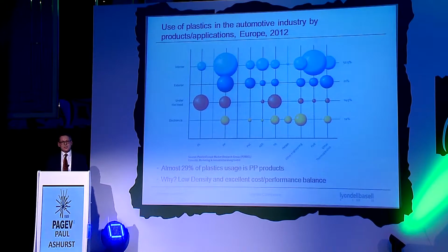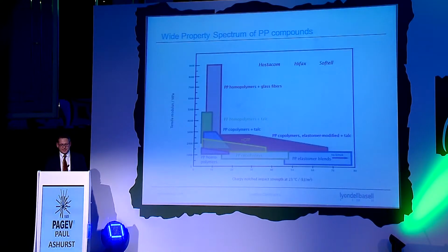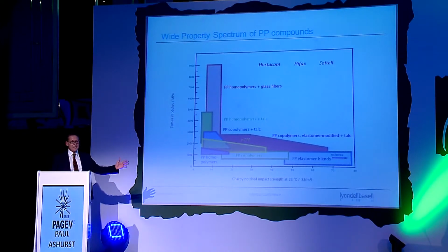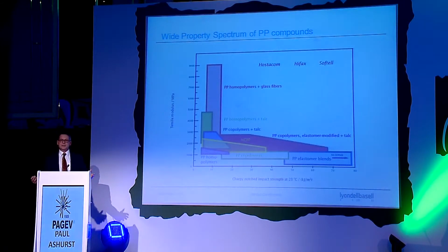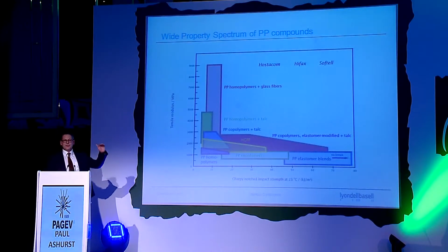It also has one of the best cost-performance balances. And cost, as you all know, is one of the most important physical factors. And through compounding, adding talc and elastomers and reinforcing agents such as glass, we can really extend the property profile of polypropylene. From the elastomeric materials for car bumpers, by adding talc, we move into interior trim areas and instrument panel applications. And if you look to the left, by adding glass fiber to PP, whether it's 20, 30, or 40%, we can really increase the modulus to levels of over 9,000 megapascals. So now we're really starting to challenge and replace engineering thermoplastics and metals.